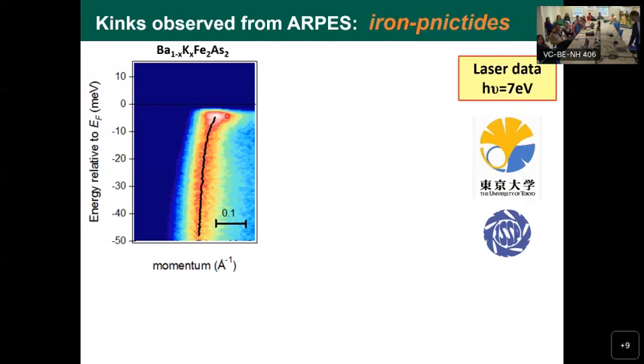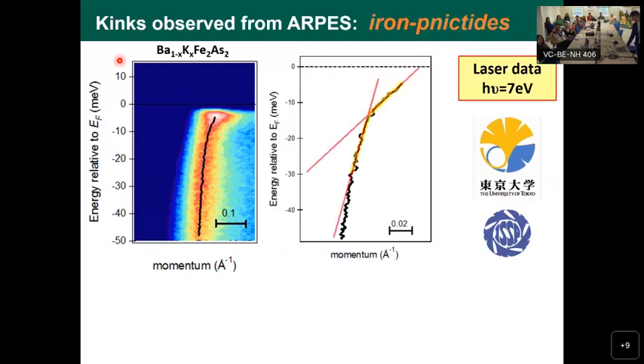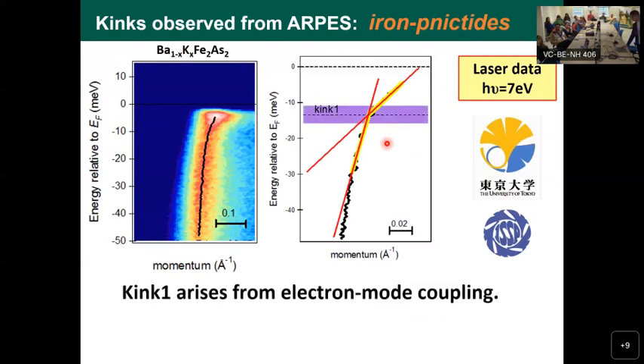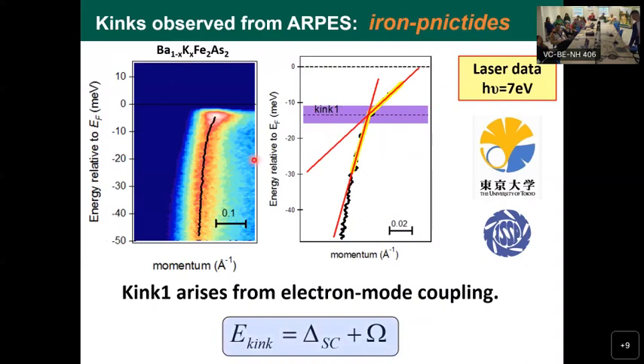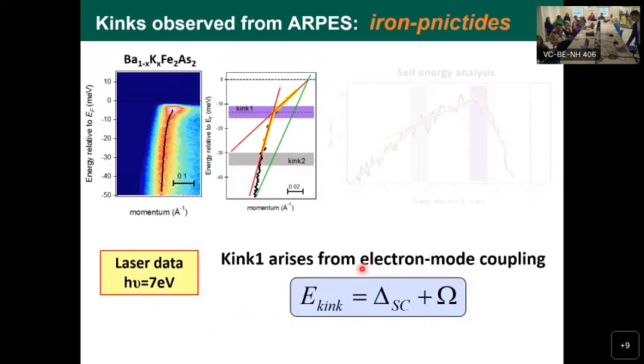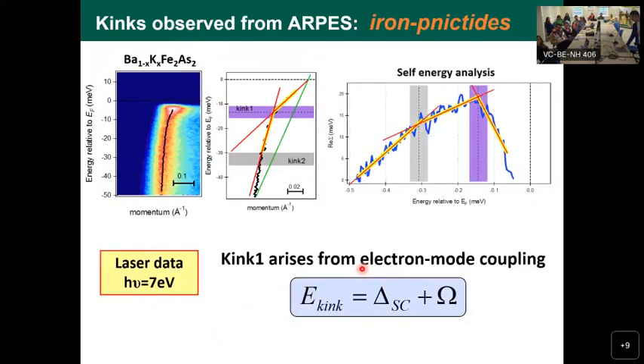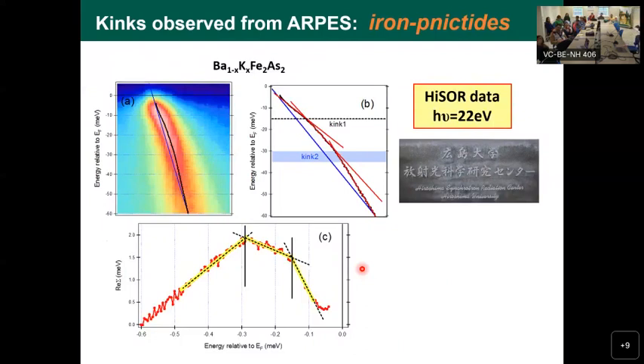We did a detailed study here. We checked how the dispersion behaves, and it shows a very clear anomaly, a very clear change in the slope, which we interpreted as kink 1. We tried to find the energy at which this anomaly occurs. This energy will be referred to as omega. And we also observed another kink. This is not enough, so we went to some more detailed analysis. We also checked these results at the synchrotron, laser and synchrotron, to have more confidence in our results, and we could reproduce the data. That was at Hiroshima, HiSOR.